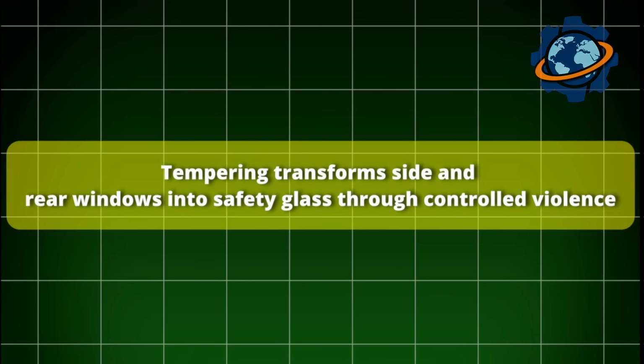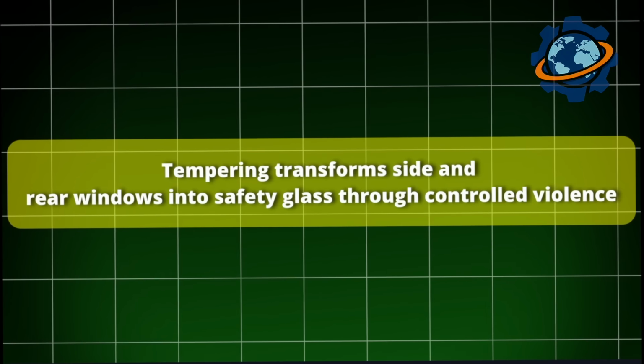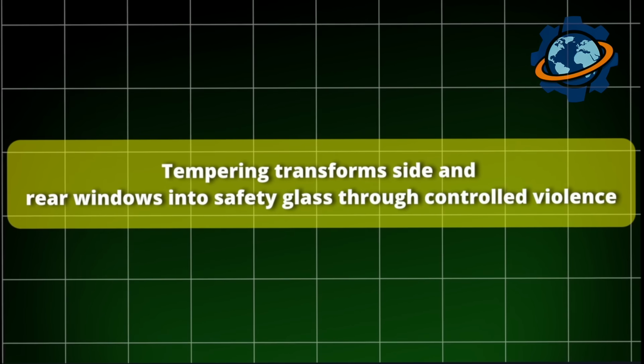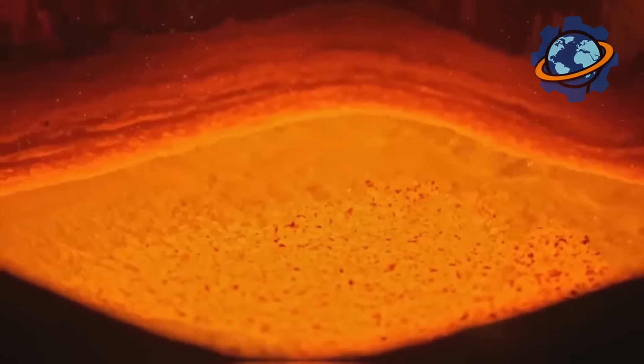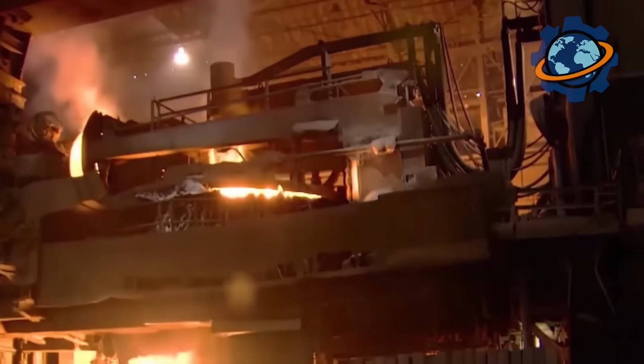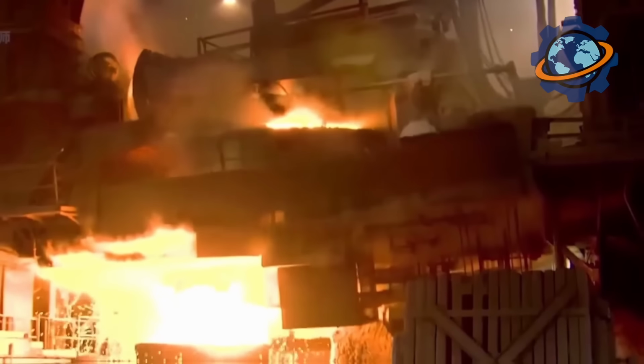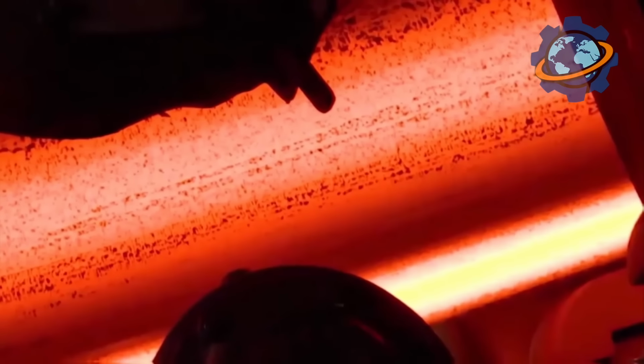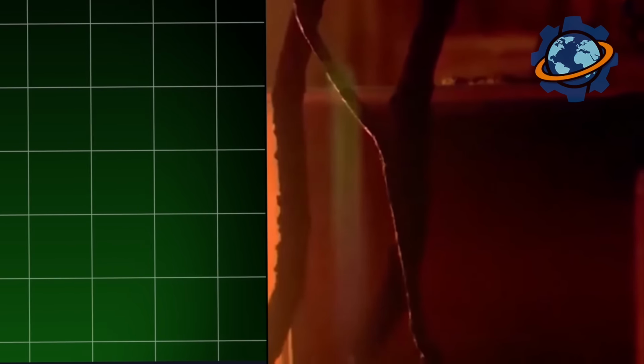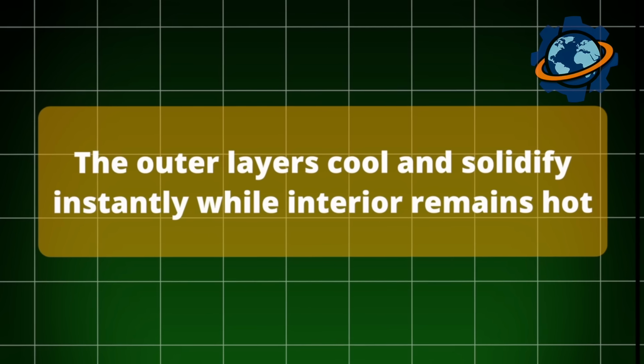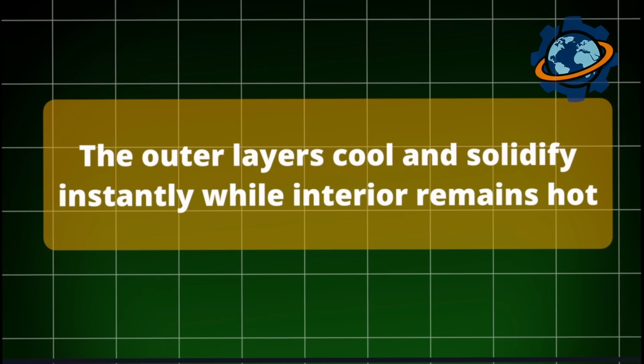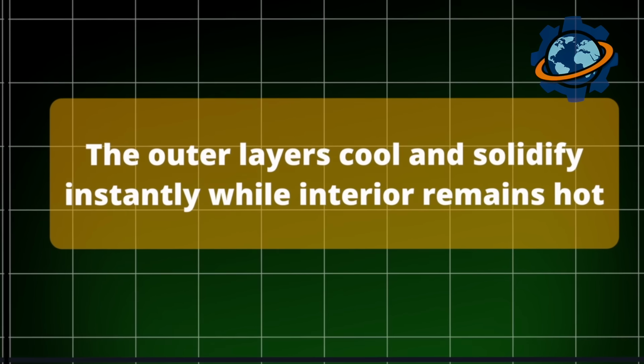Tempering transforms side and rear windows into safety glass through controlled violence. Glass pieces enter furnaces heated to 1,300 degrees, just below melting point. The glass becomes plastic, molecules mobile yet solid. Then comes the quench. Jets blast cold air across both surfaces simultaneously. The outer layers cool and solidify instantly, while the interior remains hot.